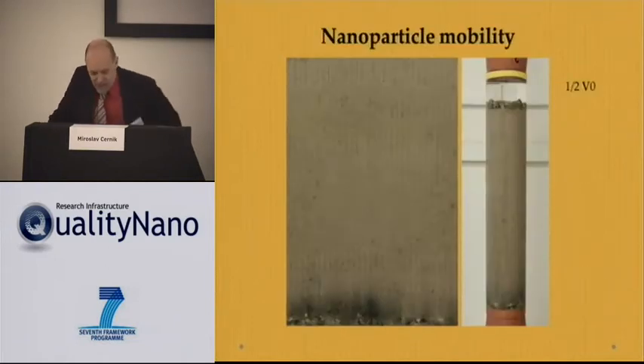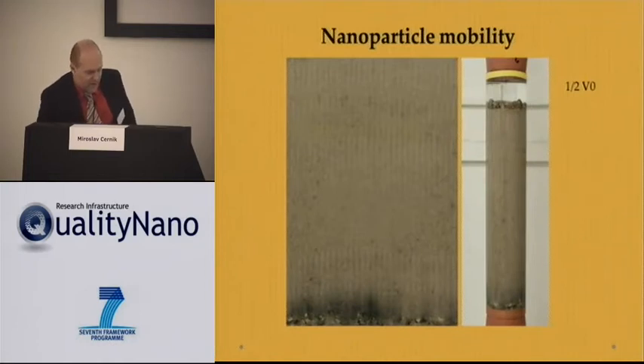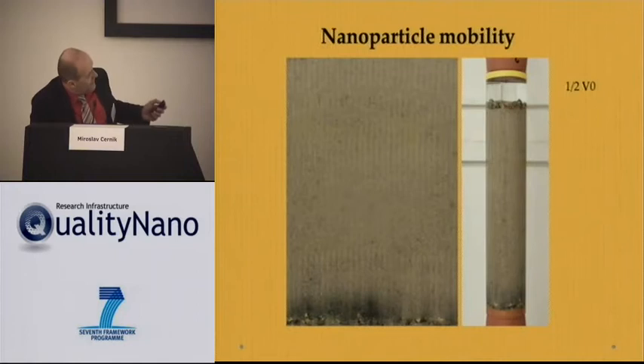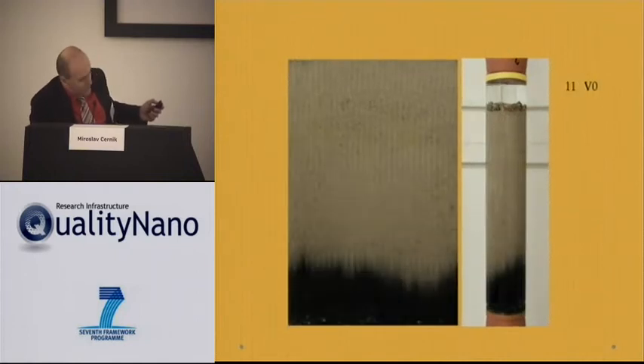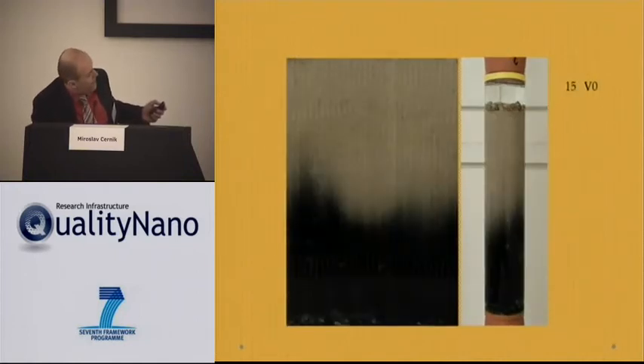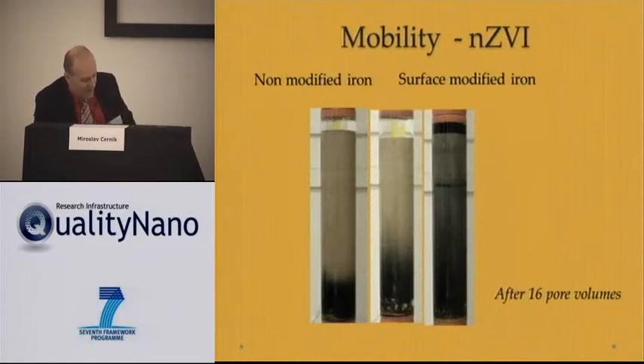So I said that the reactivity of the particles is one thing. The other important parameter is the mobility, and I have here some pictures of how the particle migrates through the laboratory column, and here is the comparison of the non-modified iron and 2 different surface modifications, and you'll see that by the modification we are able to improve the mobility of the particles significantly, which is the rightmost picture.